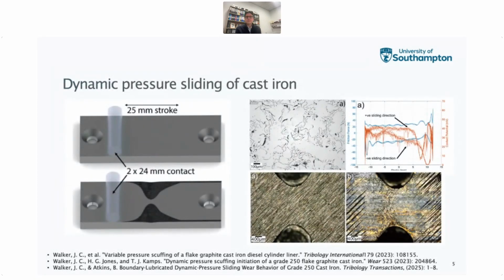So this is something we call dynamic pressure sliding or variable pressure sliding. And the idea with this is we often do a lot of tribological experiments here at Southampton where we're trying to mimic what's going on in a reciprocating sliding contact. And this is often for things like combustion engines or the piston ring interface, particularly for the next generation of combustion, which might use alternative greener fuels such as ammonia or perhaps hydrogen. And it's good if you can try and mimic the application in the lab to perhaps discriminate between different materials' behavior and the type of behavior that's going on at the surface.